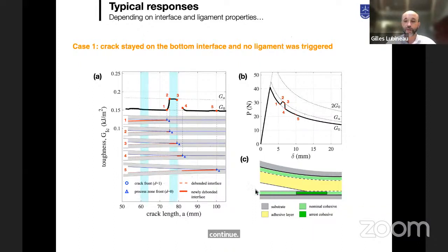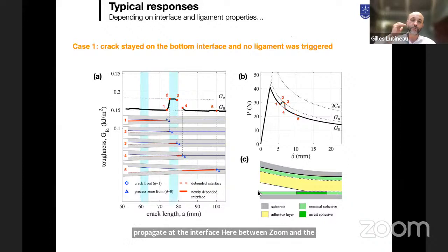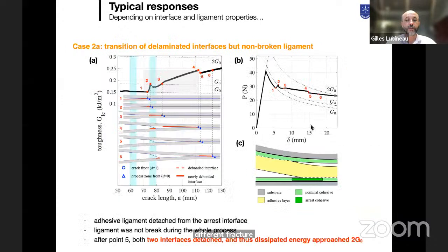Just a crack is going to propagate at the interface here between the adhesive and the substrate. And this crack is going to go through different regions with different surface properties, with different fracture properties, but without modification of the mechanism. The second thing that might happen is that when the crack is propagating at the interface on the bottom and hits the tough region, this region is so tough that the delamination is stopped here, and you introduce a bifurcation of delamination. That means the delamination will start on the top here. And then you are going to create a ligament like this, what you call a bridging ligament, that is going to bridge the top substrate to the bottom substrate.